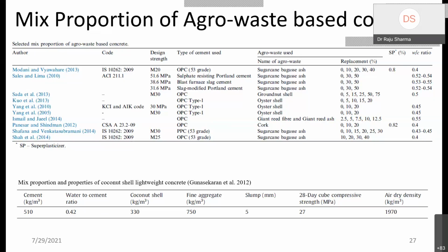Now, one coconut shell lightweight concrete composition is given below on the screen, where cement is 510, water to cement ratio is 0.42, coconut shell is 330, fine aggregate 750, slump is 5, and 28 days cube strength is 27, which is good strength, and density is the criterion to get the lightweight, so it is 1970, right? By this way people are producing different kinds of concrete, because now we don't call it a controlled concrete, we can say it's a tailored concrete, an engineered concrete rather than a simple concrete, right?